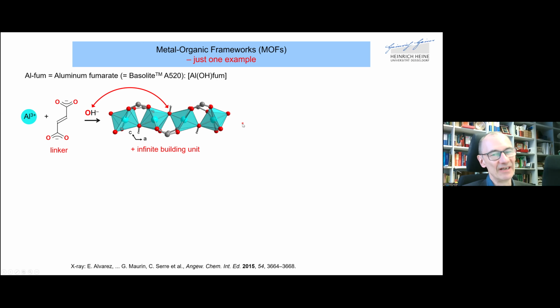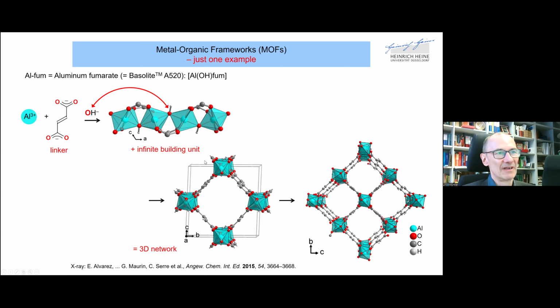So this is an infinite chain or an infinite building unit, and these chains then are connected to each other by the fumarate linkers, giving these almost square pores or channels, which are one-dimensional and extending throughout the porous network. So it's also a three-dimensional network. I should add that most of these metal organic frameworks are really three-dimensional porous networks.